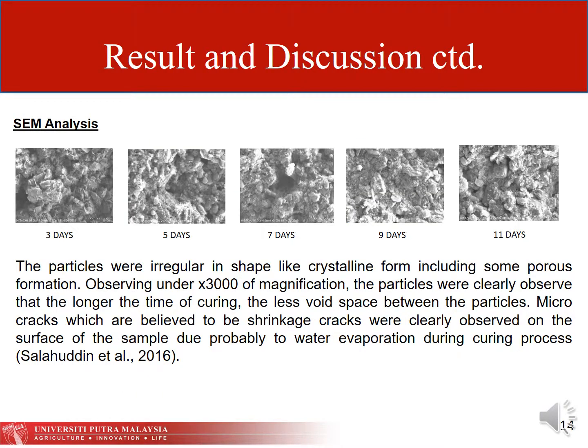For SEM analysis, the particles were irregular in shape, like a crystalline form, including some porous formation. Observing under 3000 times magnification, it was clearly observed that the longer the time of curing, the less void space between the particles. Micro cracks, which are believed to be shrinkage cracks, were clearly observed on the surface of the sample, probably due to water evaporating during the curing process.